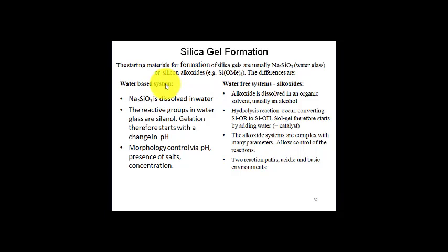In the water based system, sodium silicate is dissolved in water. The reactive groups in water glass are silanol. Gelation therefore starts with the change in pH. Morphology can be controlled via pH, presence of salts, and concentration of reactants.